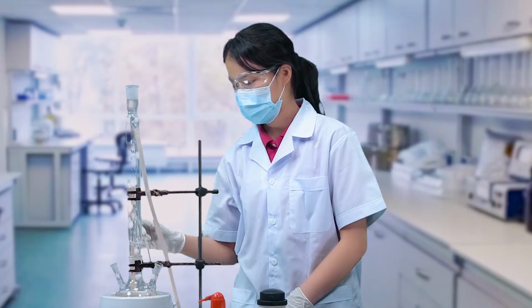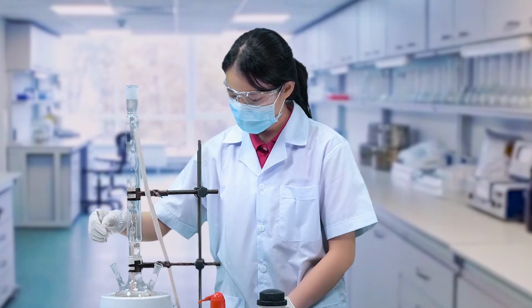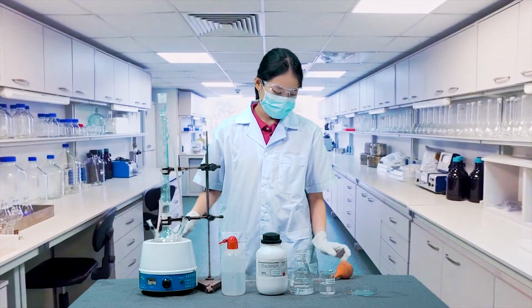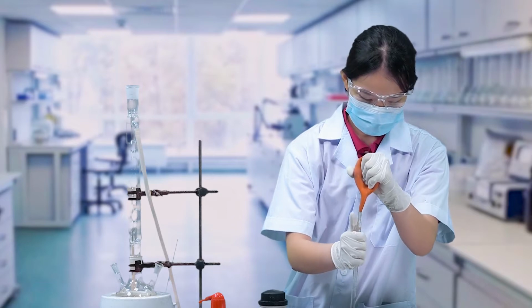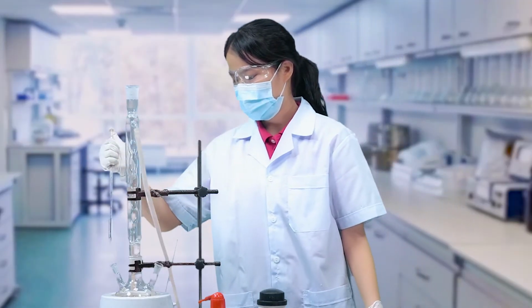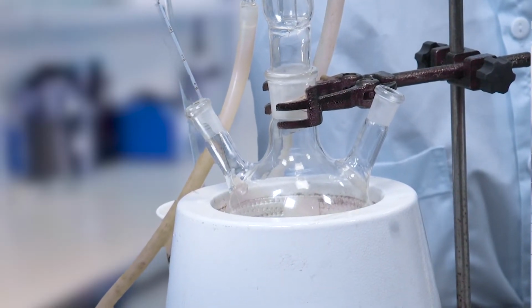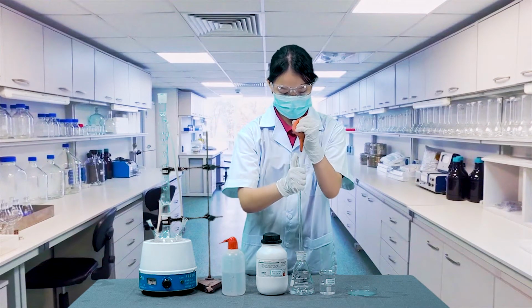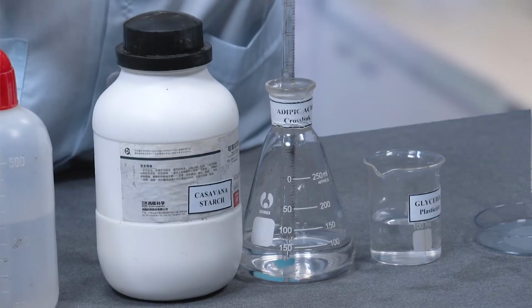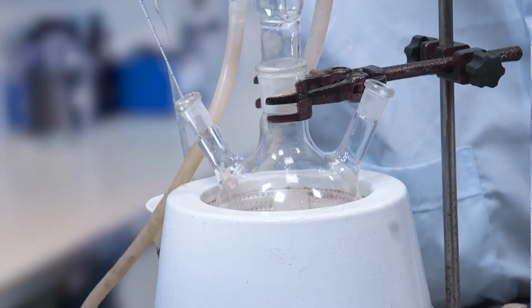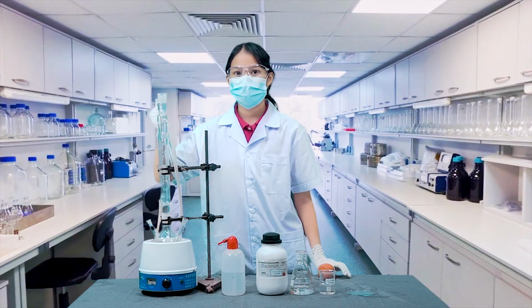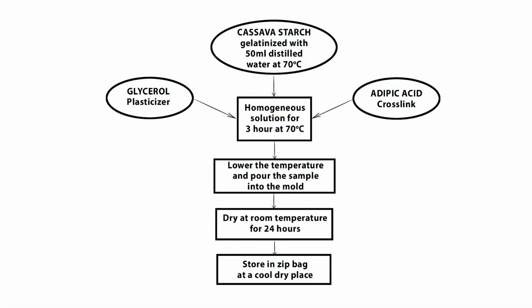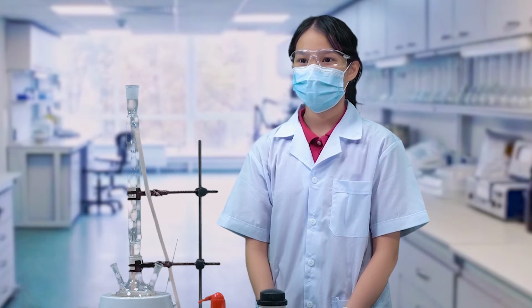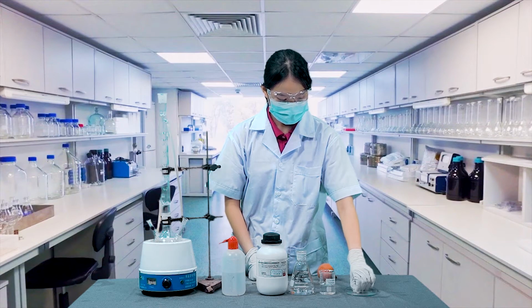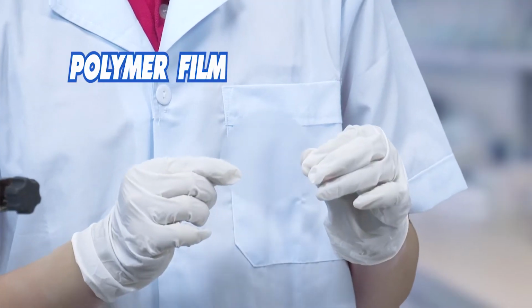From the above materials, we first gelatinize the cassava starch with 50 ml distilled water at 70 degrees Celsius. Then, we add the glycerol as plasticizer and the adipic acid as cross-link together in the solution. After stirring for 3 hours until the solution is homogeneous, we lower the temperature and pour the sample into the mold. We will dry it at room temperature for 24 hours. Then, we store it in a zip bag in a cool, dry place. Finally, we have the product, the polymer film. This is the polymer film of starch, glycerol, and adipic acid.